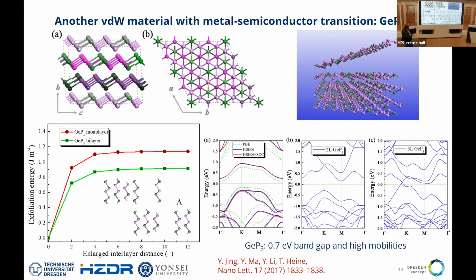And our question was, can you exfoliate that? Can you take off one layer, right? And then have a monolayer or bilayer, and what would be the properties? The properties would be very similar to black phosphorus, very narrow band gap, indirect semiconductor, something like 700 milli-electron volt band gap, very high mobility predicted. And if you go up to three layers, it becomes a metal. Okay, again, you have a semiconductor-metal transition in one material.